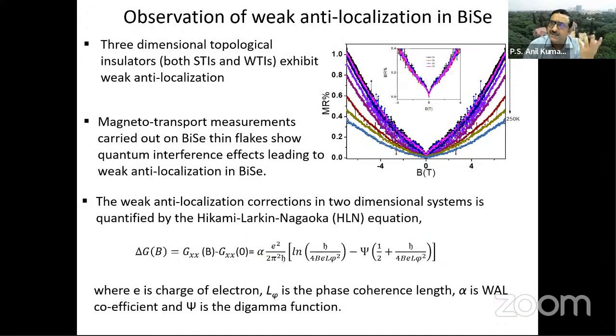So then we try to establish the electrical properties of this material. We do magnetoresistance measurements, and then we get something called weak anti-localization. In this community, weak anti-localization is generally fitted with an equation called the HLN equation. With this HLN equation fit, you get very interesting parameters, like the coherence length of this material and alpha, which gives an indication about the number of conducting channels in the system.